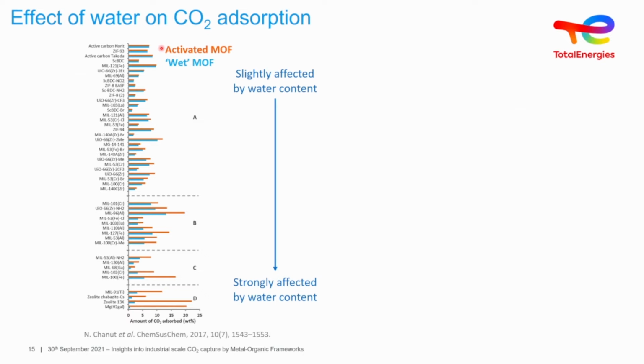We did this on a dry sample, but we also subjected the materials to water. And so we allowed the water to stabilize with the material. And then we carried out the CO2 in the presence of humidity, which was adsorbed inside the material. And we can see here, we made a ranking of those which had a little effect, medium to strong effect, and then quite a strong effect on CO2.